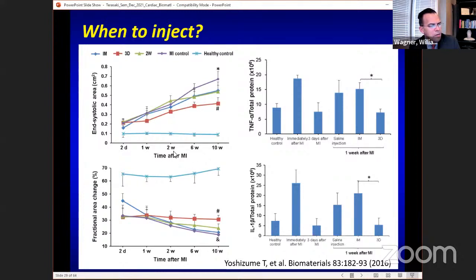This is time after MI. So at some of these, the injection is going to happen at a later time point than at others. But the key thing is just looking at the colors. You can see immediate is blue here, 3 days, and then control MI, so it's no intervention. So the one that jumps out is the red one. 3 days. And if you compare 3 days to immediate, you see the immediate wasn't good. The immediate was almost as bad as the MI control, equivalent to the MI control. So mechanically putting that material in there, at that time point into that substrate where so much is going on doesn't get you any benefit. But if you wait 3 days, you maximize benefit. If you wait longer, then you're losing more functionality.